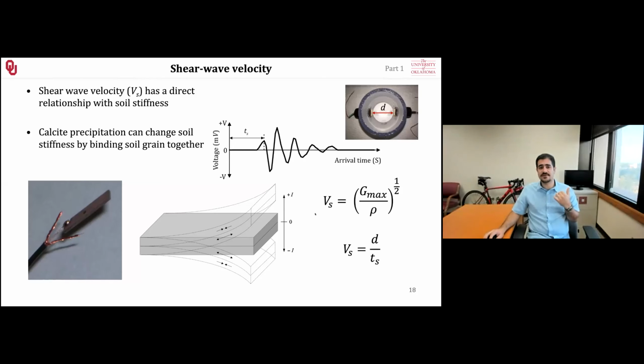We measure the time difference from the shear wave that was started from this point and received at this point, and we know the distance, so we can easily calculate the velocity of the shear wave. We know the density of the soil that we have most of the time, right? And then we can calculate the shear modulus and soil stiffness.